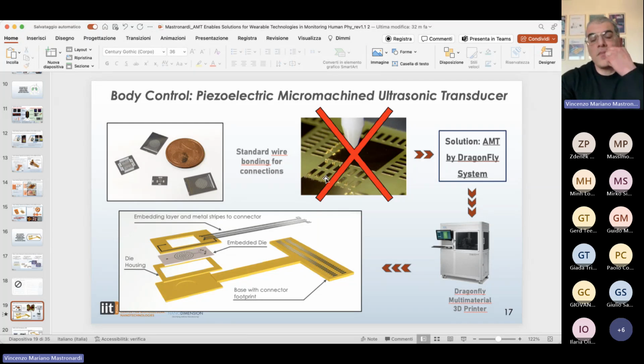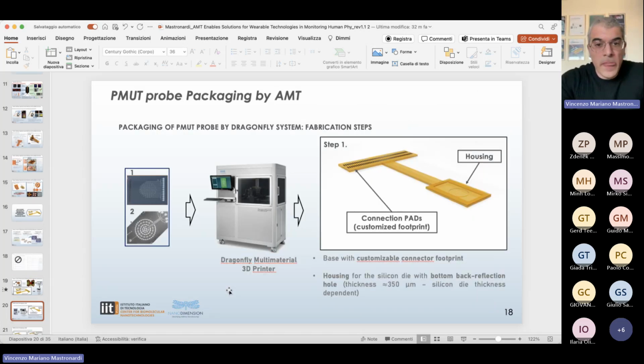So we designed this custom PCB and engineered the fabrication steps as well. They start from the printing of a base that includes a customizable connector footprint on one side, and on the other side a housing that allows us to place the silicon die, and includes also a bottom back reflection hole. In this case, the thickness of this first part of the base is up to 350 micrometers, allowing also high flexibility of the final package, which depends anyway on the silicon die thickness.